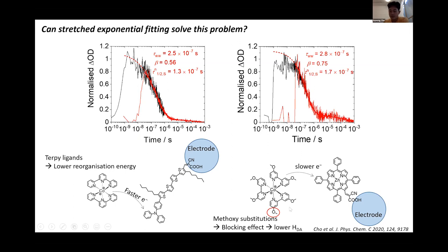However, when we employ these methoxy substituted cobalt complexes, where the methoxy group is an additional extra blocking layer to slow down the charge transfer reaction, even if it's paired with porphyrin, it showed a fairly slow electron transfer rate. Even though it showed a fairly slow decay rate, the fitting didn't really predict the exact curve measured using the faster setup. It actually overestimated the decay because this curve didn't follow the stretched exponential behavior. So in that case, the error might be even bigger. So fitting isn't always the answer to solving this problem.